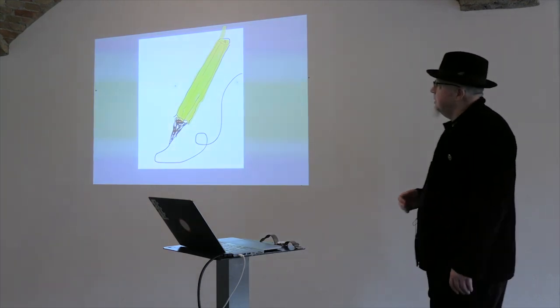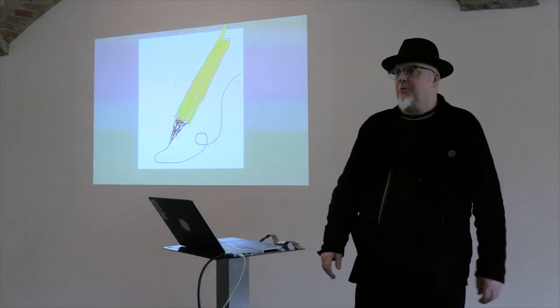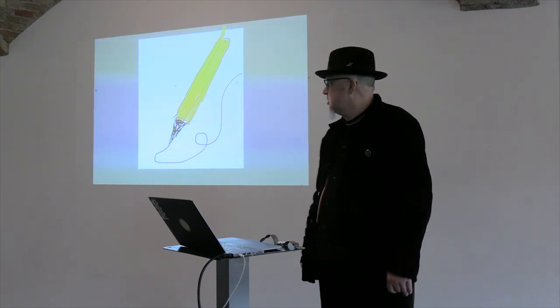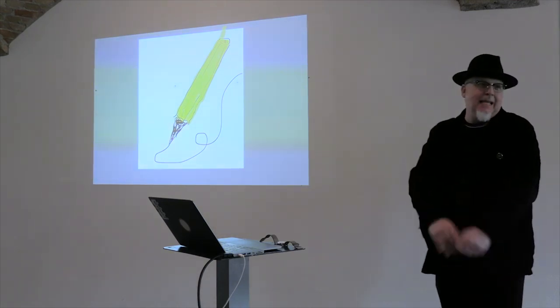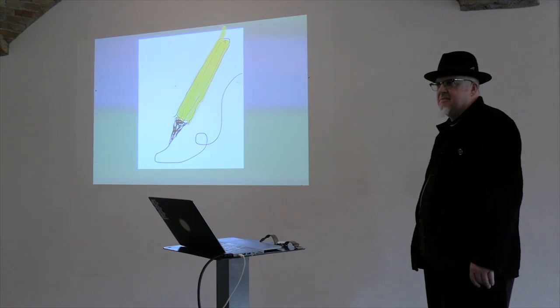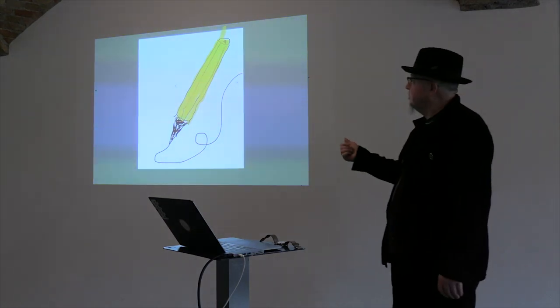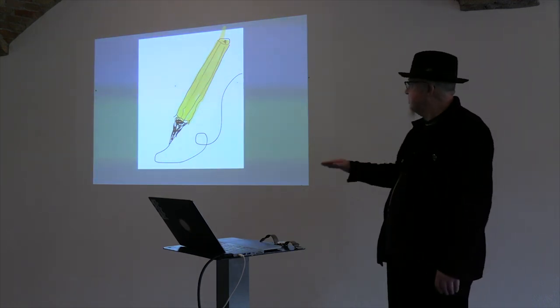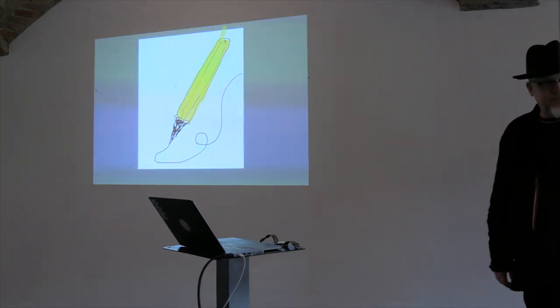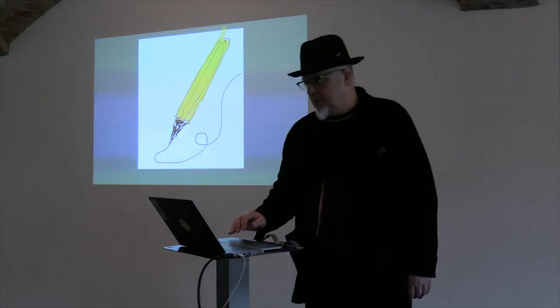What two materials — paper and a pencil — contain clay? So yeah, it's this: I hadn't worked it out for years. Okay, it's graphite in a pencil, there's wood in both, and as we know the finest papers are coated with clay. But I didn't realise for years until about 10 years ago that it was actually the stuff that held the graphite — it's fired into clay and put into a pencil. The higher it's been fired, the harder the pencil. There is a fantastic YouTube video on the production of a pencil.